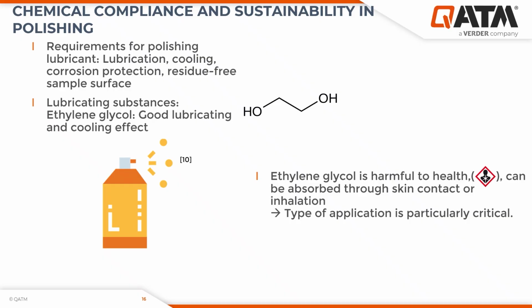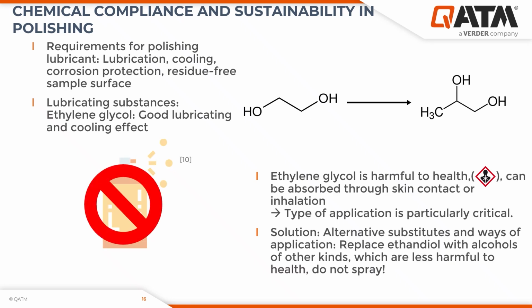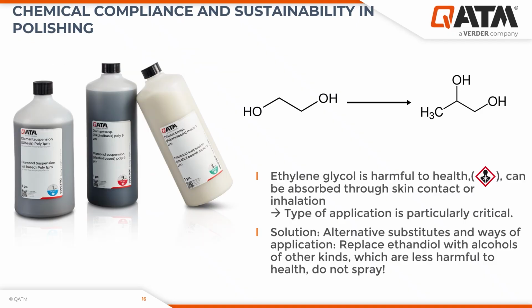And the combination of the already harmful properties of ethylene glycol with the application is particularly critical in this case. And there are several solutions to this problem. You can either substitute ethylene glycol with another diol, in this case, for example, propylene glycol, which does not show any harmful properties to human health. But also, you can try to modify your overall process, and if you're dependent on an ethylene glycol based system, try not to spray your lubricant but dose it via droplets onto your polishing system in order to decrease any risks due to the way you apply your consumable. We have a variety of diamond lubricants and suspensions that are based on less harmful systems for your everyday purposes in terms of polishing as well.